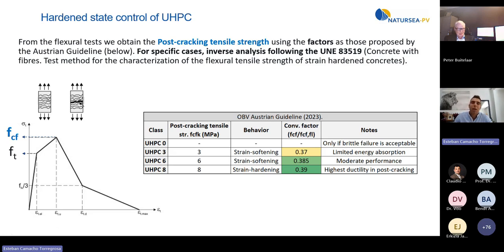The Austrian guideline suggests that, depending on the strain hardening level of your UHPC, there is a very accurate ratio between the post-cracking tensile strength of your concrete and the maximum flexural strength of your concrete. And this ratio is between 0.37 and 0.39.